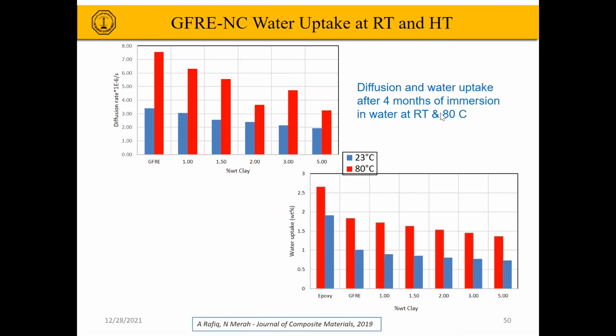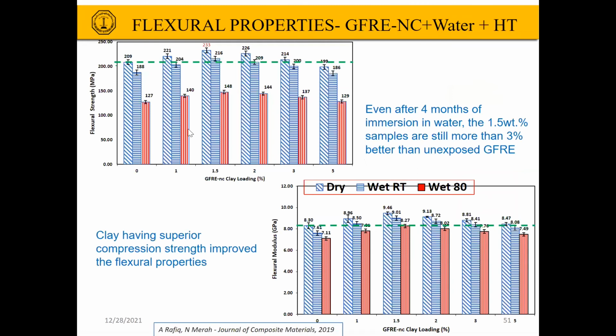Finally, we looked at the effect of temperature and water on the diffusion rate and the maximum water uptake. You can see that at 80 degrees, the diffusion rate is a lot higher than at room temperature. The maximum water uptake is higher also, which we will see as a result on the flexural strength, that the presence of water reduces the flexural strength. And immersion into water at high temperature reduces even more the GFRE.